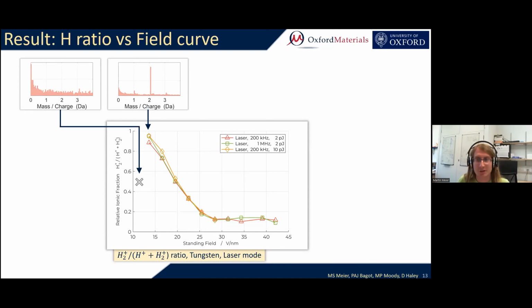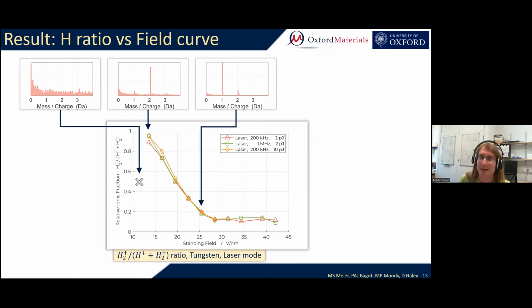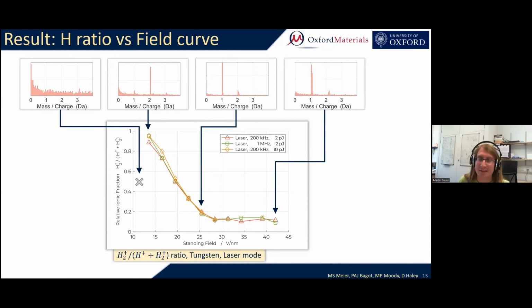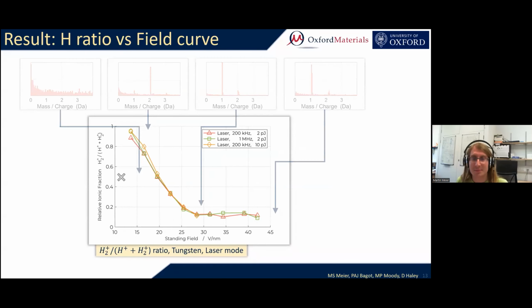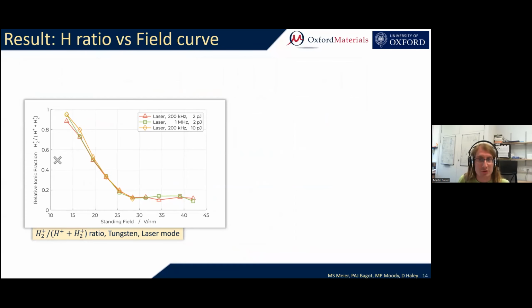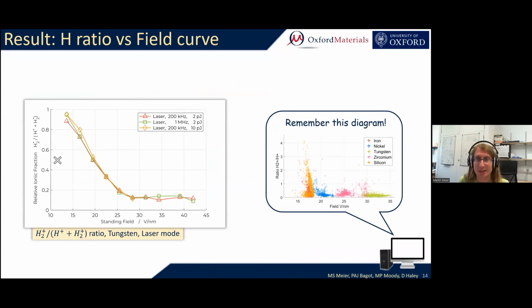And as the voltage increases, that eventually turns around, the H1+ peaks over, but as we go to very high electric fields, the hydrogen 2+ peak never disappears, and the peak height ratio appears constant between the H+ and the hydrogen 2+ peak. And that's an observation that made us very happy, because that means that we have just reproduced an observation that we make on our archive data sets. And now that we know we can reproduce this, we can actually come back many more times and make variants of the experiments to figure out what's going on.